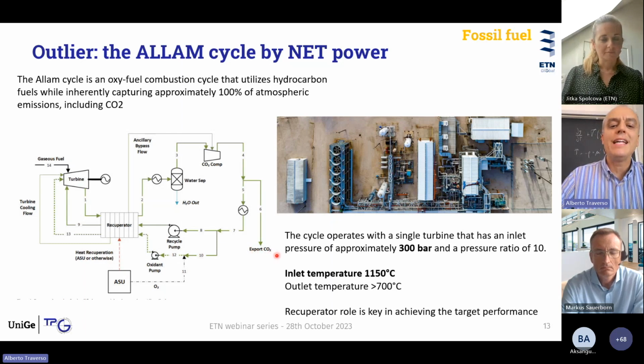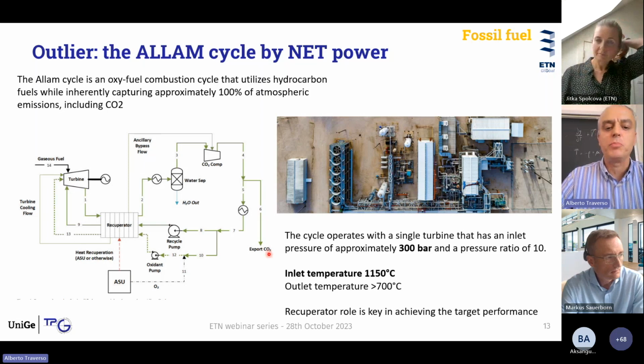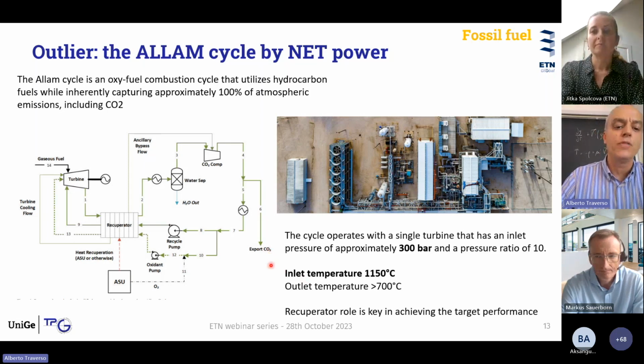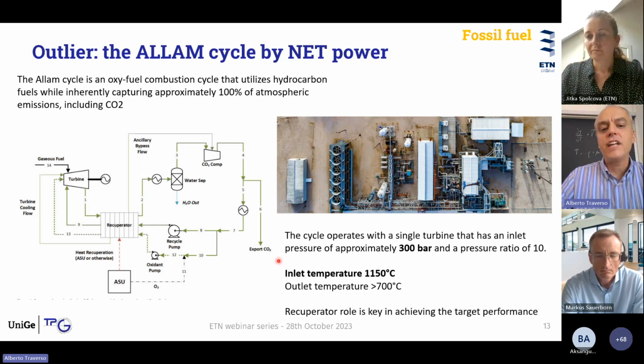And this is quite large compared to the other closed loop supercritical CO2 cycles. In the other cases, the expansion ratio was in the order of 2 to 3, depending on the specific application. The inlet temperature of this outlier turbine is more than 1100 degrees C, and it requires blade cooling. So the blade cooling flows also have to be managed in this case. It is relevant to say that in the previous cases, all the turbines were uncooled.